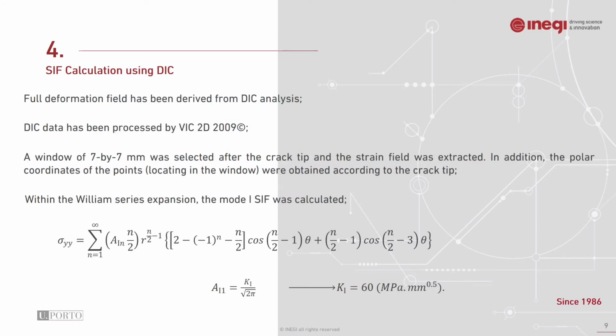Stress intensity factor calculation using digital image correlation is presented in this slide. The full deformation field has been derived from digital image correlation analysis, and the data was processed by VIC2D software. In order to obtain the result, a window of 7 by 7 millimeter was selected exactly after the crack tip, and the strain has been monitored in this window. So the polar coordinates of the points located in the window have been obtained according to the crack tip. By using the Williams series expansion, it was possible to extract the mode 1 stress intensity factor as can be seen in the formulation. So the stress intensity factor was calculated as 60.